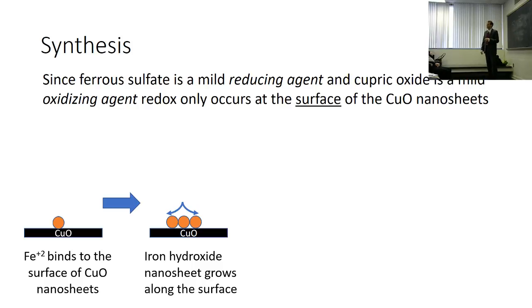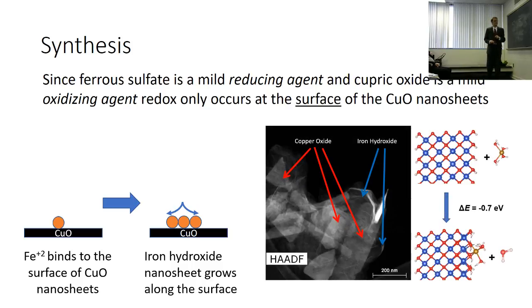If it's being oxidized, and the redox is occurring, it's only happening on the surface of the copper oxide. Similar to before, how we had the oxidation only occurring on the surface of the soft template. Now it's occurring on the surface of the copper oxide. I got some help from molecular modeling people, Victor Batista's group, and they showed that the binding of this iron complex to the surface is favorable. It's good. So there's some credence for this. It's not just me saying stuff.